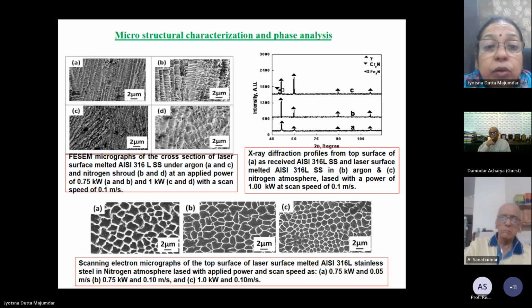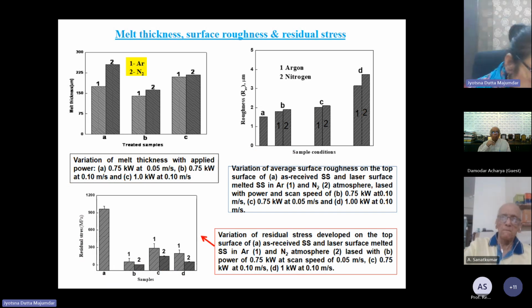So this is interesting in case of this concept, surface melting. Laser processing is so unique that you can do anything using this laser on the surface. So particularly we saw very interesting results on surface melting. Whenever you do surface melting of an alloy system, you introduce a refined microstructure. In addition to that, you get redistribution of the alloying elements in such a fashion that there is homogenization of alloying elements all throughout the microstructure, which is not there in as-cast and rod product. So this homogenization and refinement combined cause a lot of improvement of different properties, particularly corrosion resistance. So this philosophy we applied in many alloy systems, and we got similar results.